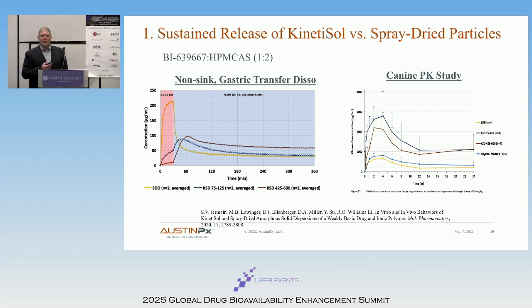So the tool compound was from Boehringer Ingelheim. This is all published information in a joint collaboration with Austin and Boehringer Ingelheim. Essentially, they had a poorly soluble API, and they made spray-dried particles, and then they used the KinetiSol technology. What happened was with the spray-dried material, it was dose dumping, and you can see on the left-hand side that the top curve, material is dissolving in simulated gastric fluid. Meanwhile, the KinetiSol particles remained intact, they didn't dose dump, and they were able to release when, during the two-stage dissolution experiment, it switched over to FaSSIF. And this bore out in canine studies, where you had higher exposure due to the sustained release of the KinetiSol particles compared to the spray-dried particles.